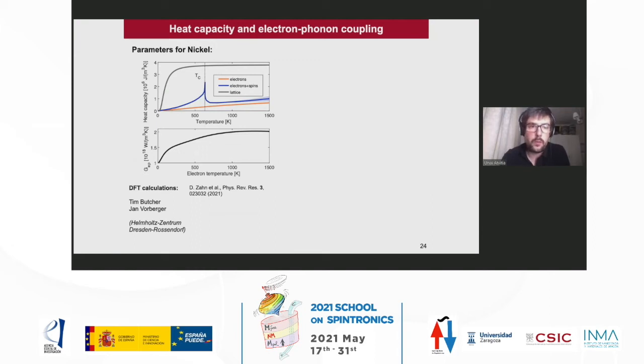Looking at the figure, the heat capacity of the lattice is basically constant above room temperature, which is where we work. The electrons follow a linear dependence on the electron temperature, which is common to assume since it comes from the free electron approximation. The spins show a critical behavior around Tc, which is also very common.